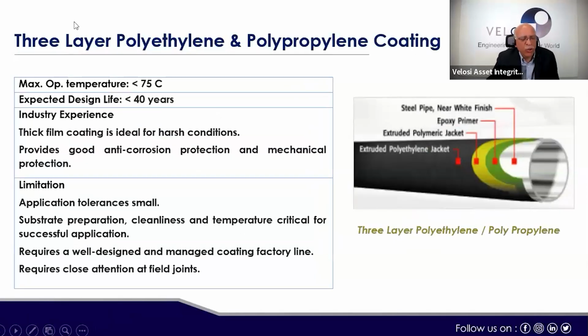Now, this is a more popular kind of three-layer polyethylene or polypropylene coating, which normally works effectively up to 75 degrees Celsius. Expected design life 40 years. Thick film coating is ideal for harsh conditions, provides good anti-corrosion protection and mechanical protection as well. Next, the application tolerance is small; the substrate preparation, cleanliness, and temperature are critical for successful application. It requires a well-designed and managed coating factory line, and close attention at field joints.